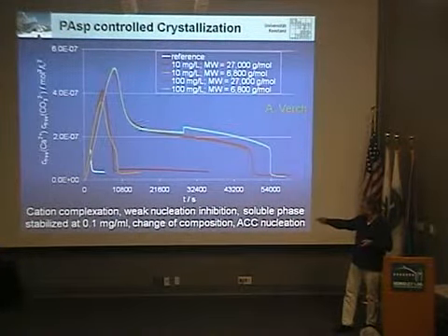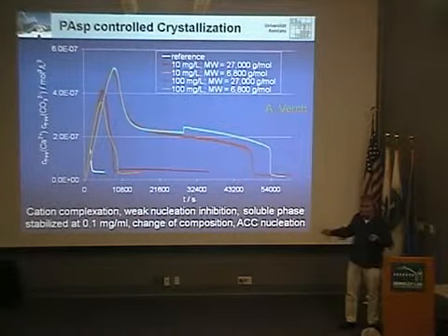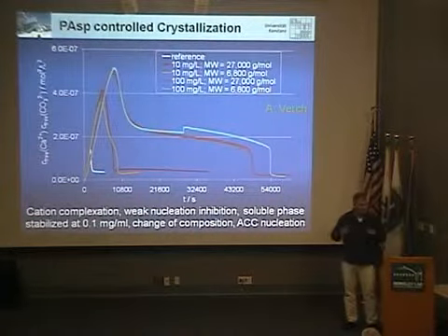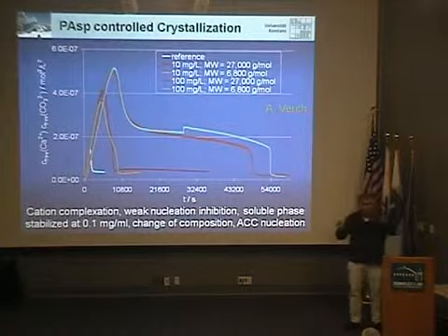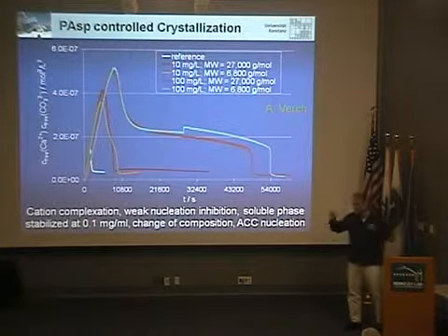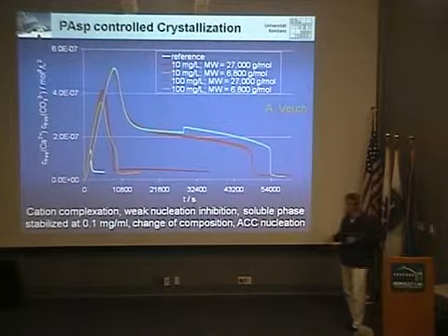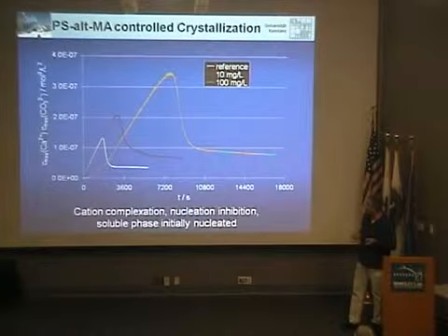After nucleation, we see something which is much more soluble than amorphous calcium carbonate. It also changes the composition, so you see that too, and that's also something Laurie Gower found. The liquid precursors are never the same time-wise; they change their composition until they nucleate. In the end, you get amorphous calcium carbonate, which then crystallizes. So you can directly see it quantitatively in this titration setup.